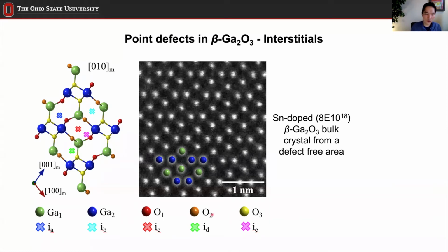And then there are 3 different oxygen positions, which are colored differently, but less important for the matter that we discuss here. All right, so those are the atom positions. But I want to point out the fact that there are also a lot of empty gaps in between those atomic columns, and those potentially become the interstitial sites, right? So it's possible that a defect can form right at that position, meaning that some atoms, whatever that is, can be stuck at the gap here, right?